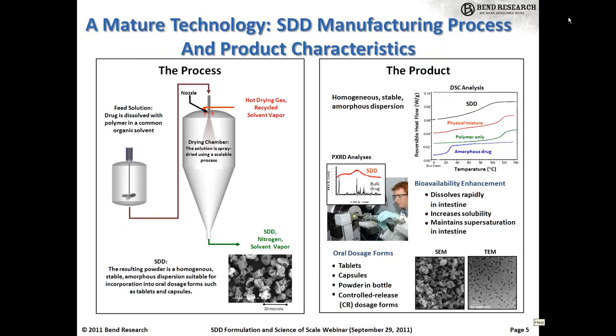Let's move into sort of the introductory material on spray-dried dispersions. This is kind of a real high-level overview of the process and the characteristics of spray-dried dispersions. So on the left here, at the highest level, what's done is the drug and polymer are dissolved, or sometimes polymers are dissolved in organic solvents or a mixture of solvents, and they're spray-dried into an expansion chamber, and the powder is collected. Dana's going to talk much more about that, so I'll leave it at that for now. But when done properly, what's achieved is a high surface area particulate with typically a morphology, kind of what's shown here in this SEM image. So you have kind of a collapsed sphere or a spherical morphology.